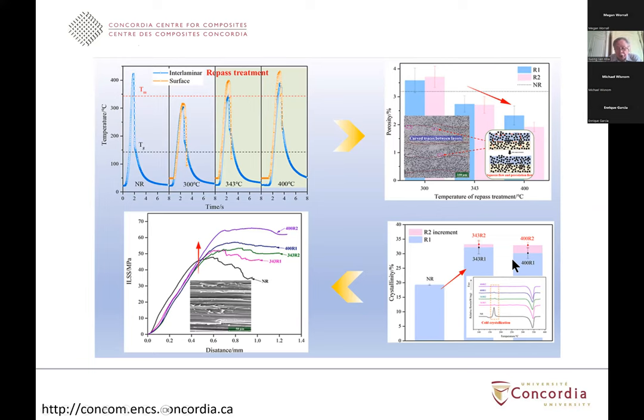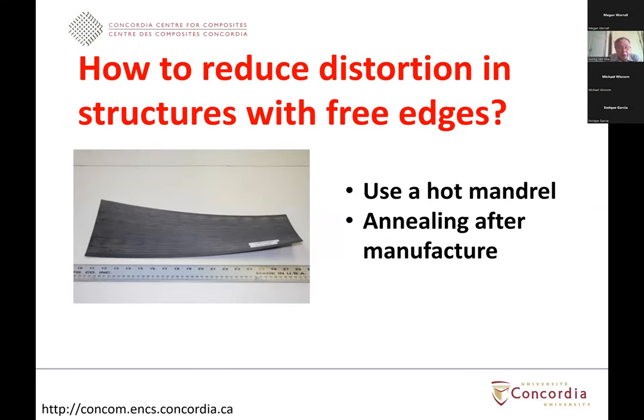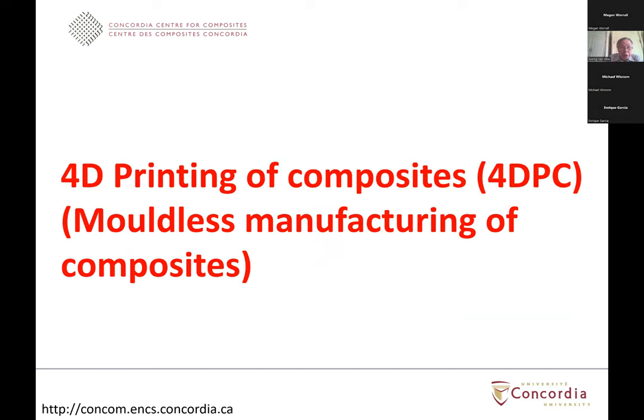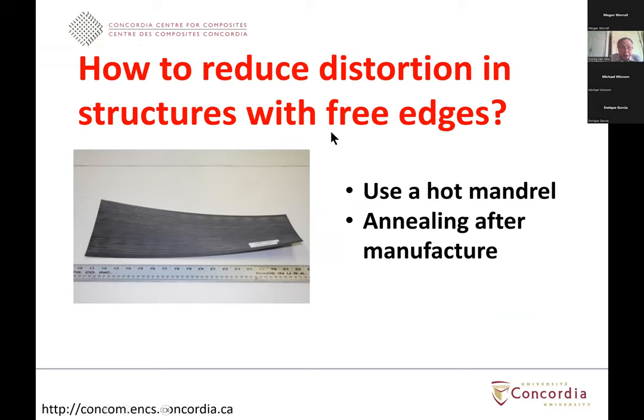So the last issue in terms of automatic fiber placement for thermoplastic composite is reduced distortion of the structure with the free edges. Now there are many different kinds of structure that we can make. You can have a complete cylinder where you don't have the free edge, but you have something like a free edge, like a flat plate like this. This one here is a laminate, a unidirectional layer, all fibers along one direction.